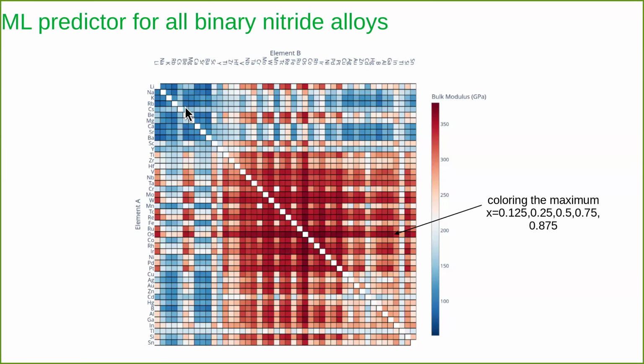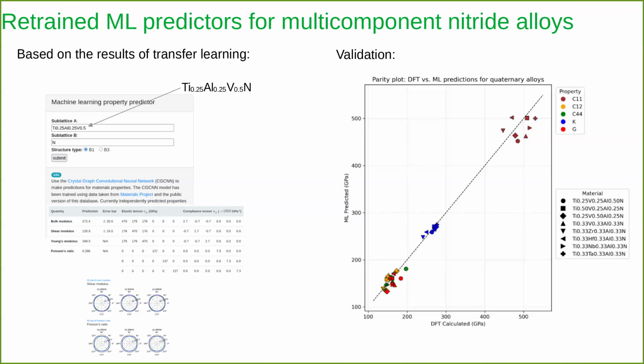So, for example, if you would like to take a titanium-based alloy, you go here, and you will see immediately that titanium, zirconium, hafnium, vanadium, niobium, this part, the industry-relevant materials, all have very high bulk modulus. Similar figures we have achieved for the shear modulus, and similar figures we can generate for the Cij components. It's included.